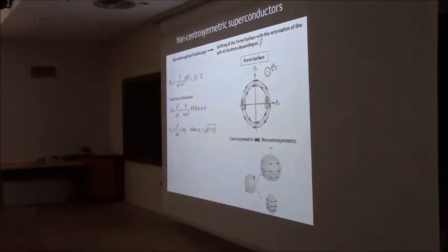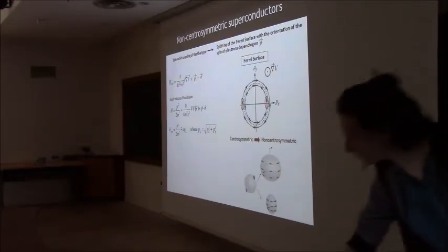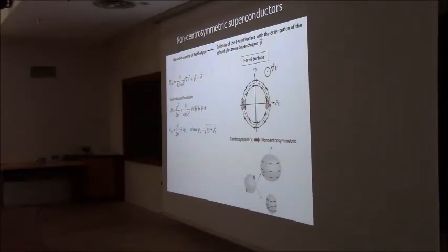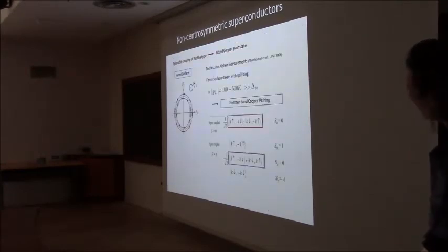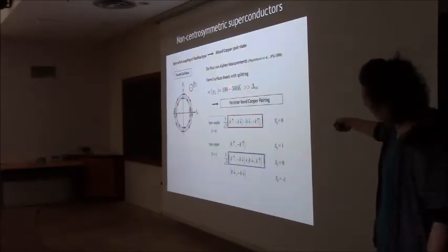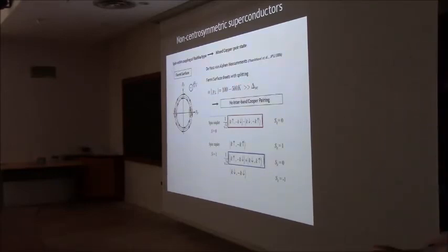This has very strong consequences on the superconducting state, because when I said it's a singlet state, it means that you need these 2 degenerate electrons. But here you cannot do that. You see, these 2 are split by a large energy, which is larger than the superconducting gap. So you cannot make this pairing. The splitting is like 500 Kelvin, 100 Kelvin, which is much, much larger than the superconducting gap.